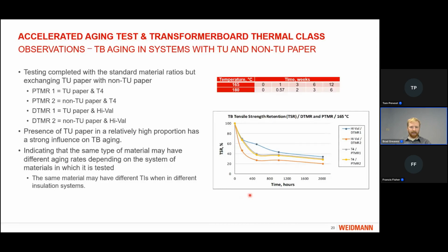We see a similar thing on the power transformer ratio side. However, there's much less difference here. The one with thermally upgraded paper is slightly higher than the other. And just to point out, I didn't mention before, but this is the tensile strength retention on the press board after these aging periods. So this is really the effect of the thermally upgraded paper on the press board aging in these two instances.